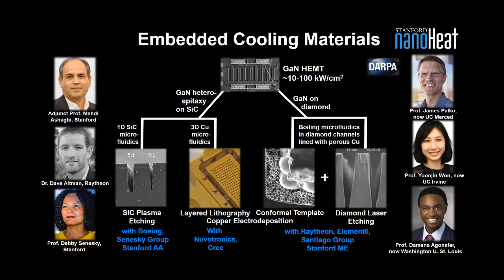In one case, we built the heat sink in silicon carbide, which is the substrate material below the HEMT. Another case, we made it using fluid optimized routing in copper. And then another case, we made a porous structure, and we laid that porous structure inside etched diamond channels that Raytheon can produce using a laser etching technique. And so they made microfluidic channels from diamond. I call this the $2 million heatsink, because we made a couple of them, and you can figure out how much money we got. But they were incredibly high performance and got us enormous rates of heat transfer and explored the limits and were able to control the phase. So we built all of these with these different collaborators.